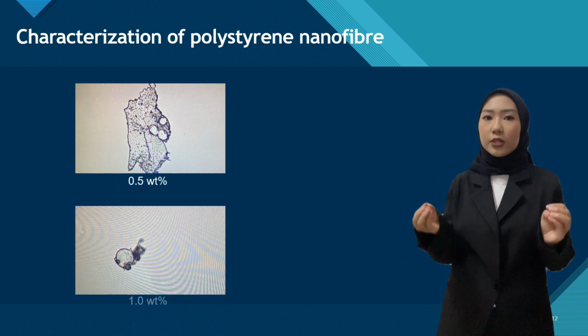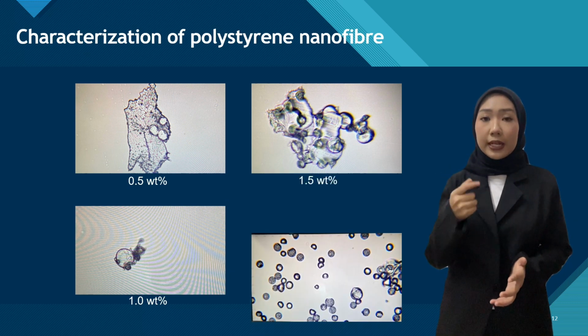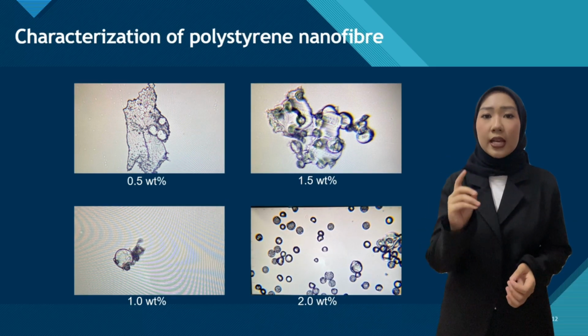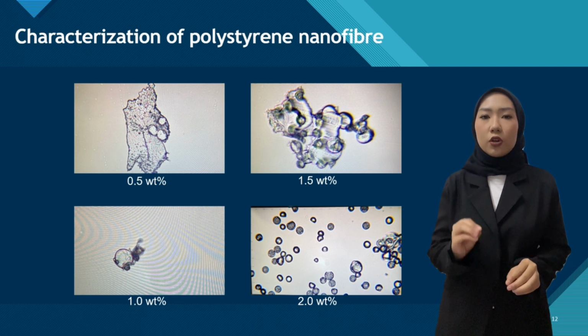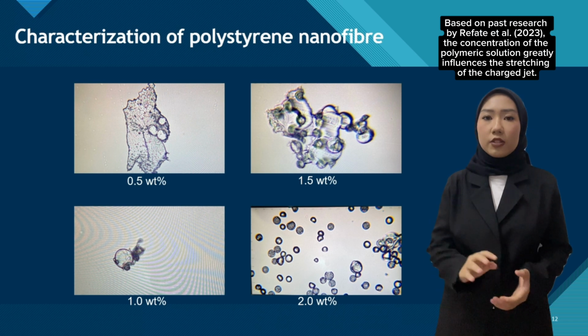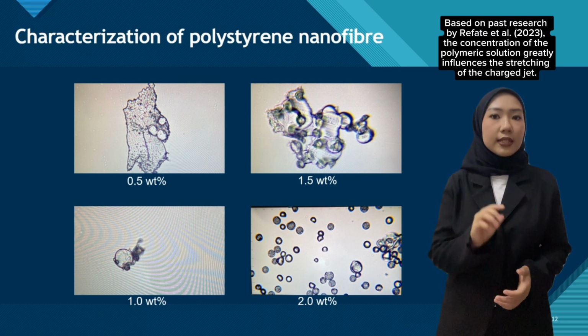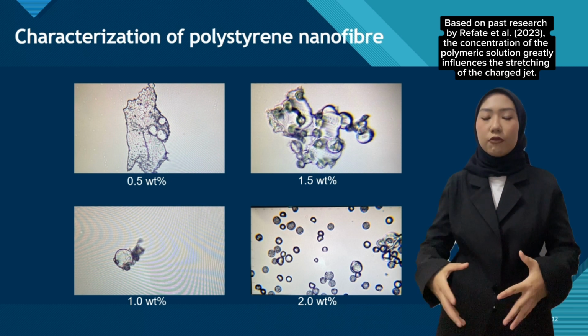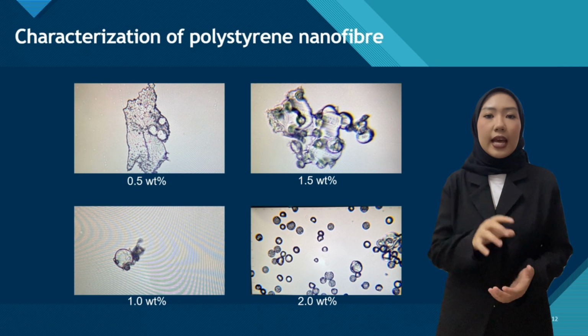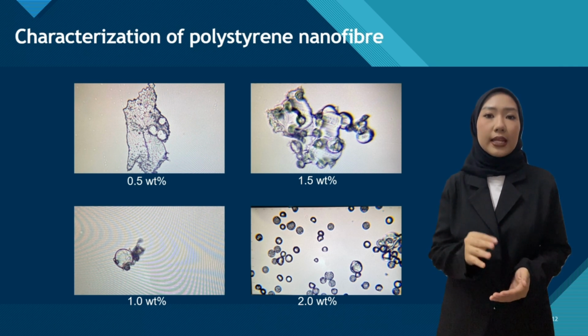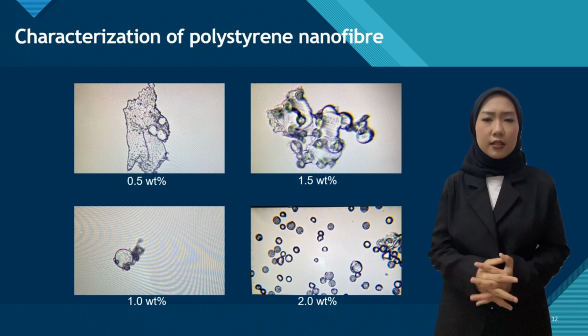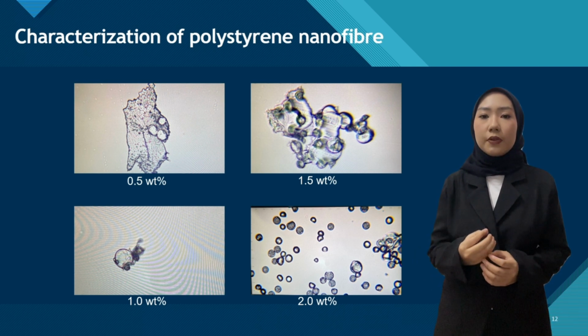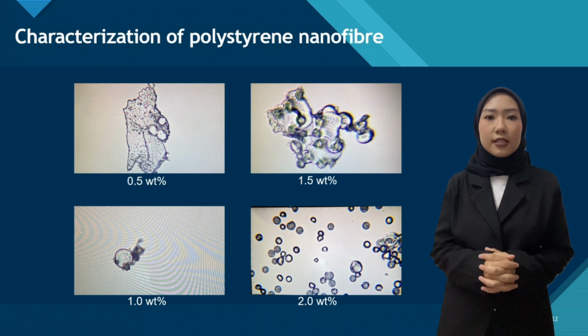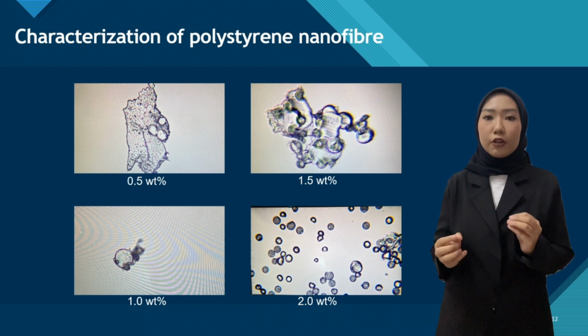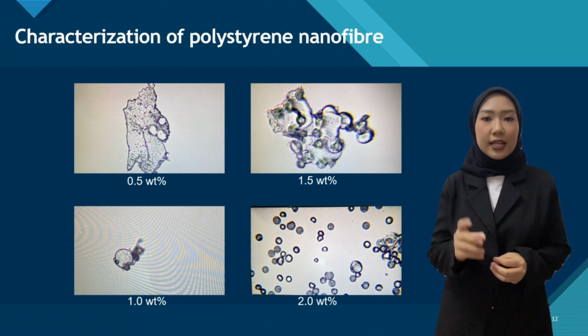The production of nanofiber using the solution of expanded polystyrene and xylene failed. When the product was observed under the microscope, it was in beads and droplets with no string of nanofiber. This may be due to the low concentration of expanded polystyrene. Based on past research by Refate et al. (2023), the concentration of the polymeric solution greatly influences the stretching of the charged jet. At low concentration, the combined effects of the applied electric field and surface tension cause the entangled polymer chains to break up before reaching the collector. This results in the formation of beads or beaded nanofibers, leading to a high average fiber diameter until a critical